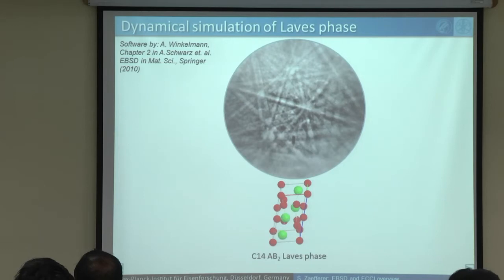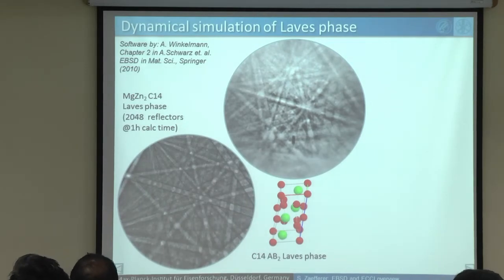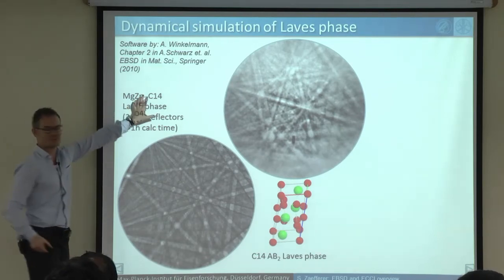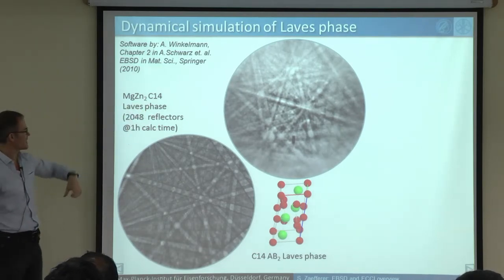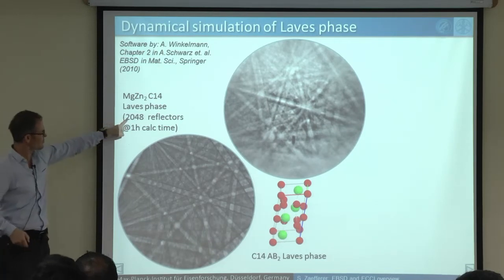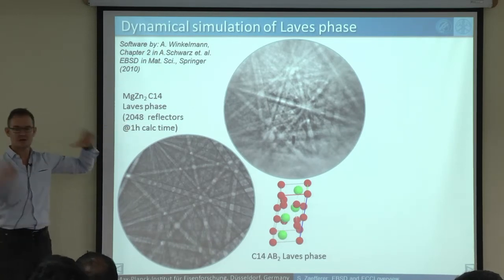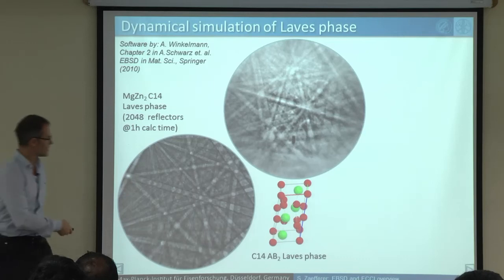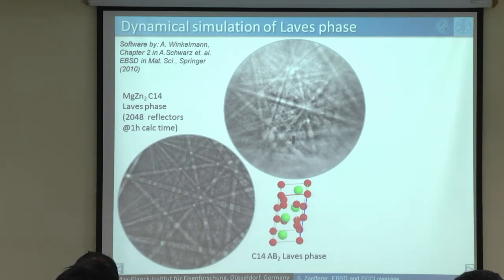So I took this diffraction pattern. I admit it's not the most beautiful one, but accept it for the moment. And I calculated the prototype of the Laves phase, of the C14 Laves phase, which is magnesium zinc. This is the prototype which you find in the international tables. I used 2048 different lattice planes to calculate using the software. And then I compare. And if you compare, you will find, in terms of geometry, everything is correct.